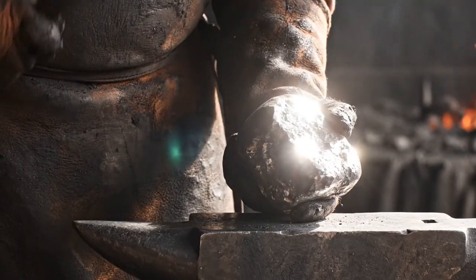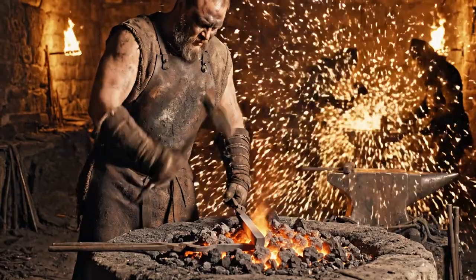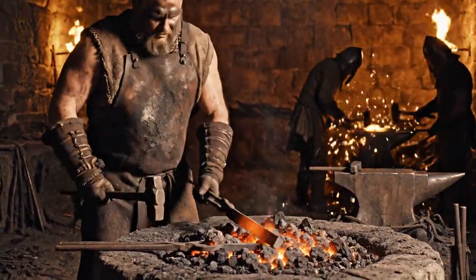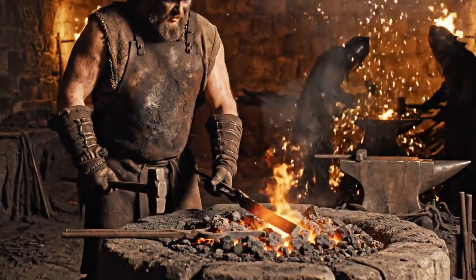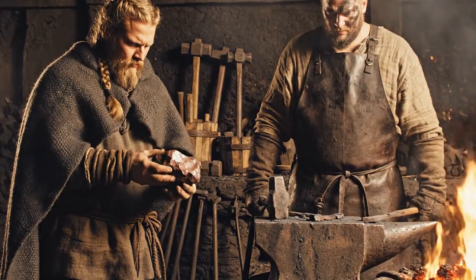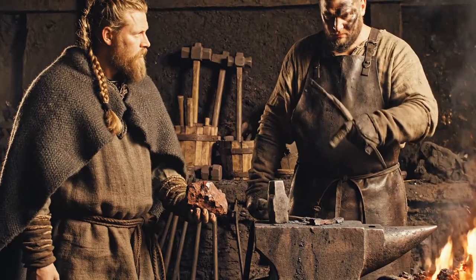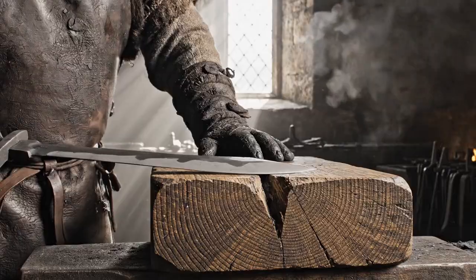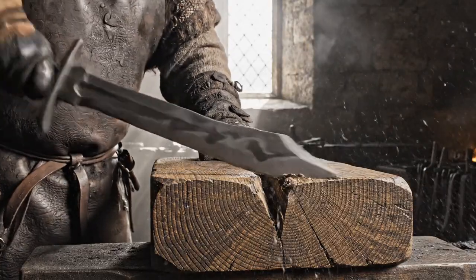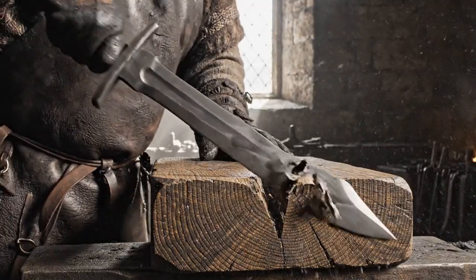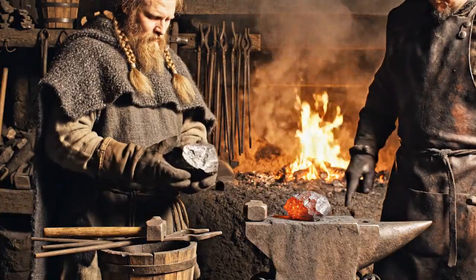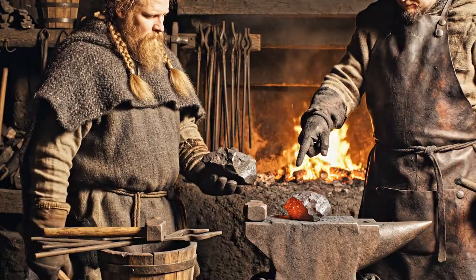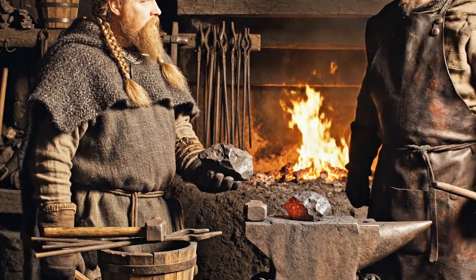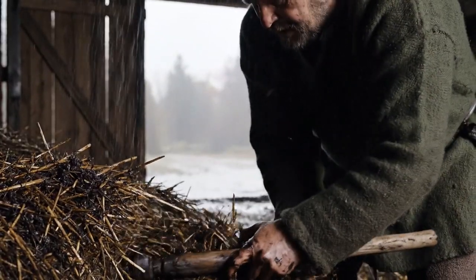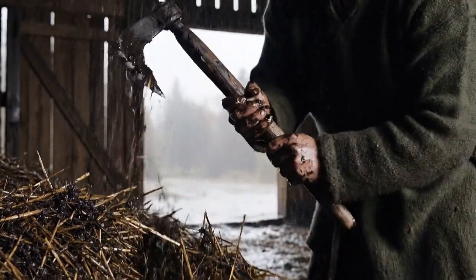No modern steel mill would produce it intentionally, and yet archaeometric studies across Europe have confirmed that phosphoric iron was not a defect. It was deliberately used throughout the entire medieval period. Why? Because phosphorus does two things that medieval blacksmiths discovered empirically centuries before anyone understood the chemistry involved. First, phosphorus increases hardness. A phosphoric iron blade holds an edge better than pure wrought iron.